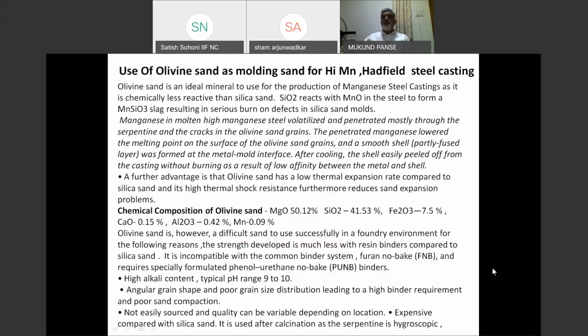Is use of olivine sand. Olivine sand is used in Hadfield steel. Also, you should check the chemical composition, and if FeO content, CaO content are higher, you should check on it. MgO content as given in the specification is 50%. You should try and see that it is more than 50%.